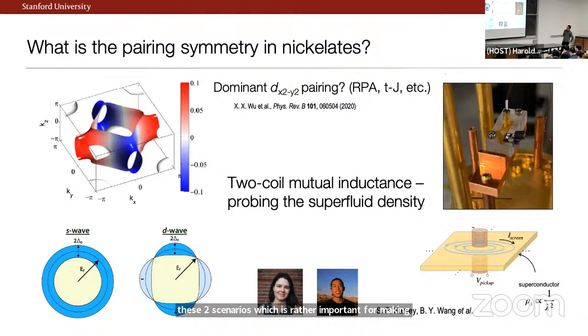So the way we went after this problem is to try to measure the superfluid density. That is, what is the density of superconducting electrons running around in our system? And the way we did this was using a mutual inductance measurement. So imagine you have this little solenoid magnet on one side. You put an AC magnetic field. What we're doing is basically seeing how much magnetic field gets through our narrow sheet of superconductor. And it turns out that that mutual inductance measurement gives you a measurement proportional to this superfluid density. So this work was led by Shannon and Bai in our group.